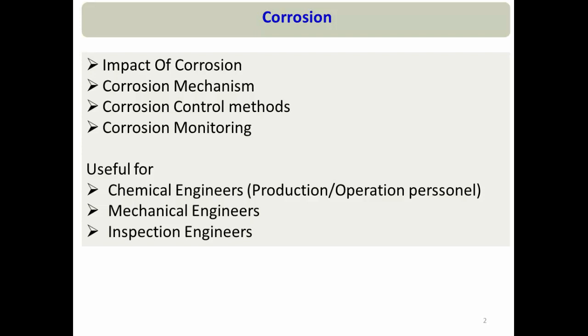We also need to understand corrosion mechanism when handing over equipment. For example, we can't flush a stainless steel line with fire water because fire water contains chloride. And when equipment manholes open, we need to understand where pyrophoric iron could be. So from operation to equipment handover to safety, all these things become clear when we understand corrosion mechanism thoroughly.